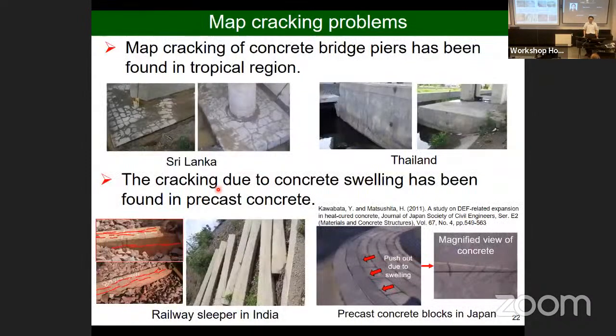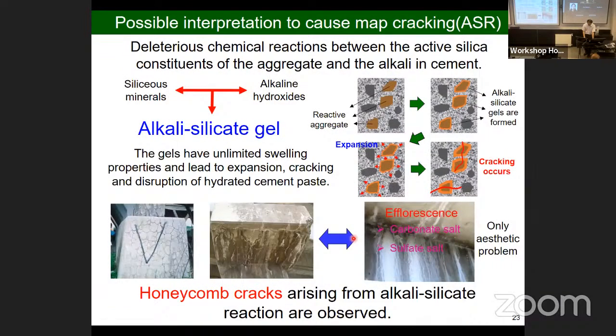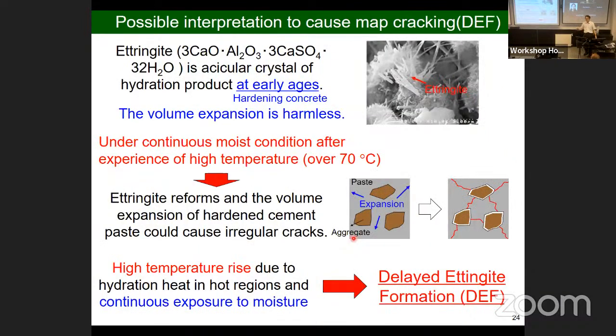And also recently they discussed the map cracking issue. This is Sri Lanka, this is Thailand. If we see this kind of map cracking from the Japan side, probably Dr. Yamada will explain the ASR issues later, but generally we always think that this is ASR. But they always say, no, this is not ASR because we don't have reactive aggregate. We have never experienced it. They always insist, we have never had ASR. And they always say, okay, the temperature is very high, that's why DEF. That is just a simple explanation. They just exclude ASR according to their experience.